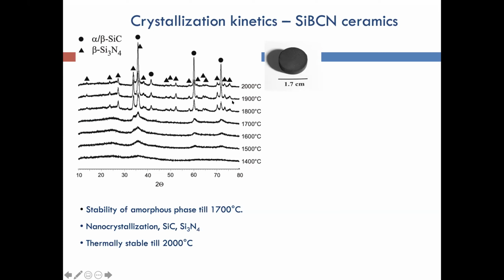And even the crystallites that they form, that is silicon nitride and silicon carbide, are very, very fine. I mean, they are in the order of around 50 to 80 or less than 100 nanometers, distributed in a matrix of boron, carbon, and nitrogen. And that is the most interesting part of this microstructural design.